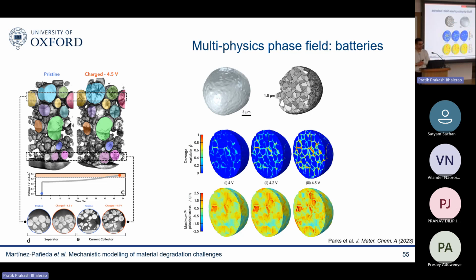I think they say Tesla is going to come up with a million cycle battery, which apparently is based on replacing those grain structures by a single crystal. Because of course, grain boundaries are the weakest link. So if you replace those grain boundaries by a single crystal, maybe you get a super battery. We can test those ideas with those models.